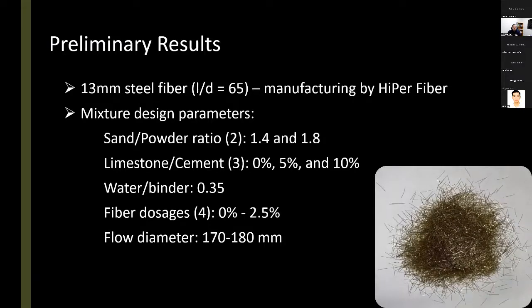Fiber dosage, I told you some initial testing that we did, we learned that with some modifications to our concrete printer, we can add up to 2.5% by volume of these 1/2 inch steel fibers, which was very exciting. As far as I know, this is the highest amount of steel fiber that has been used for construction 3D printing, 2.5%. So we wanted really to go deeper and see what's the impact on the properties of materials.